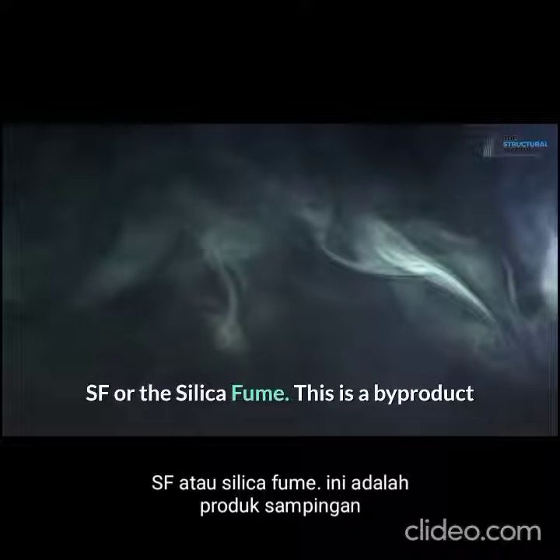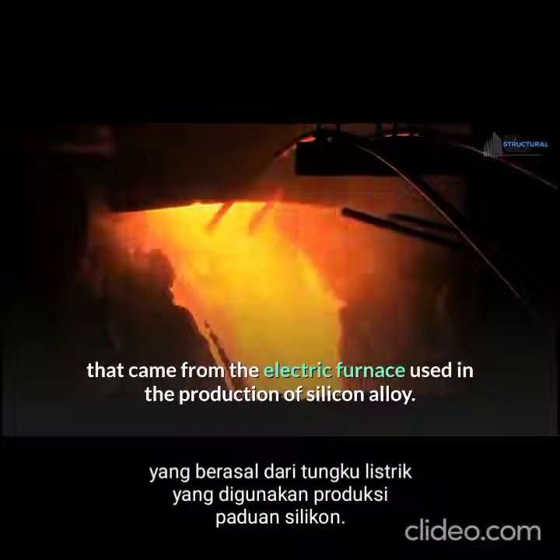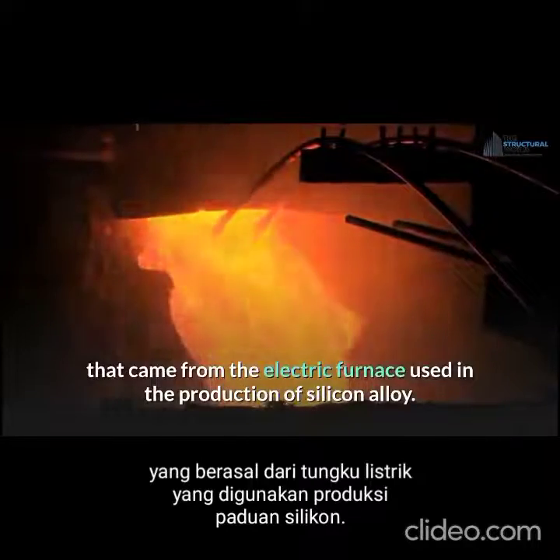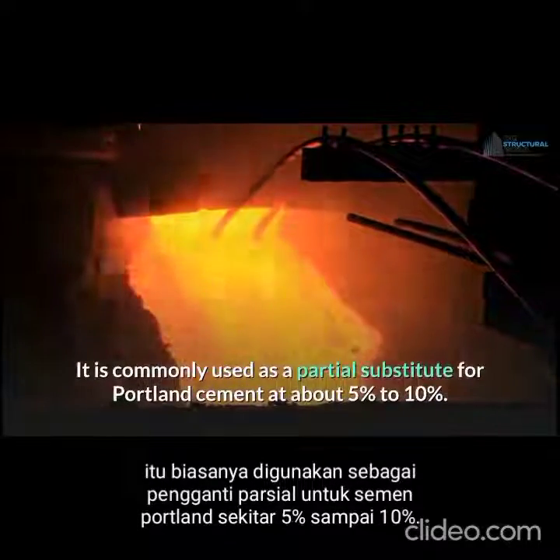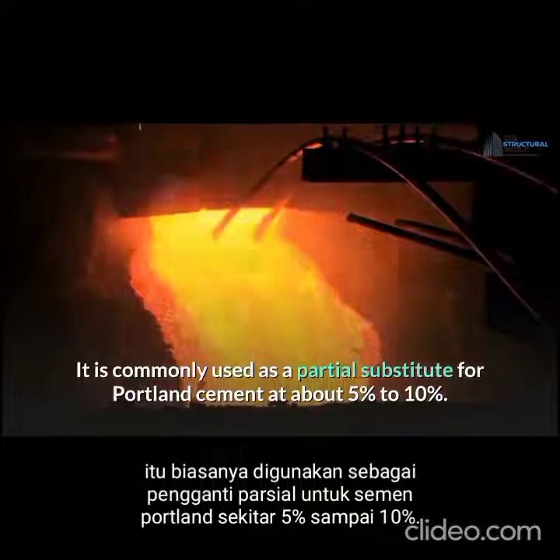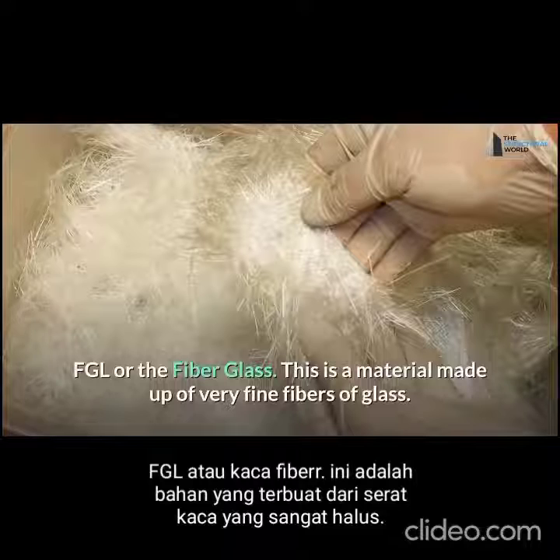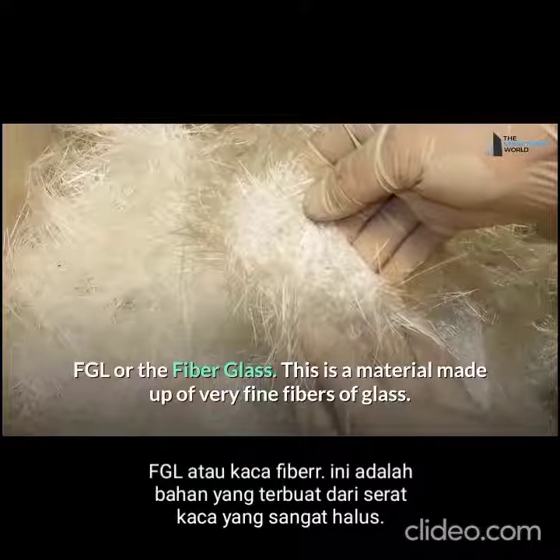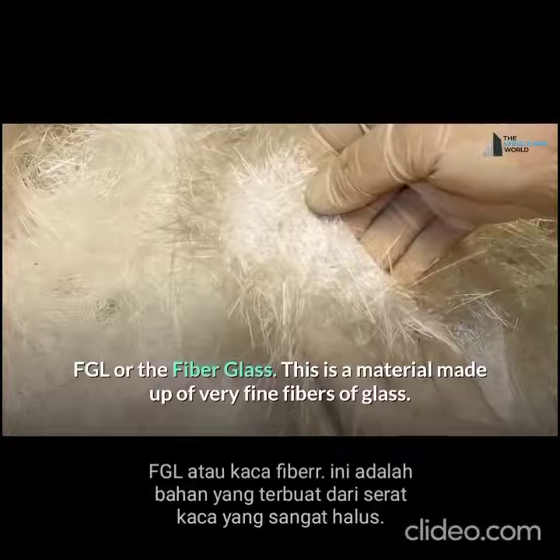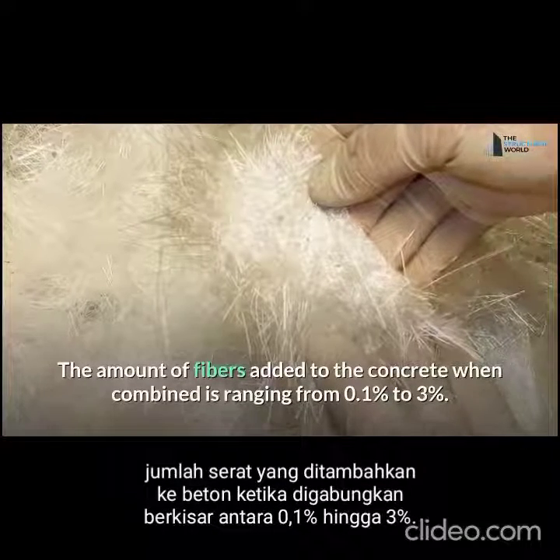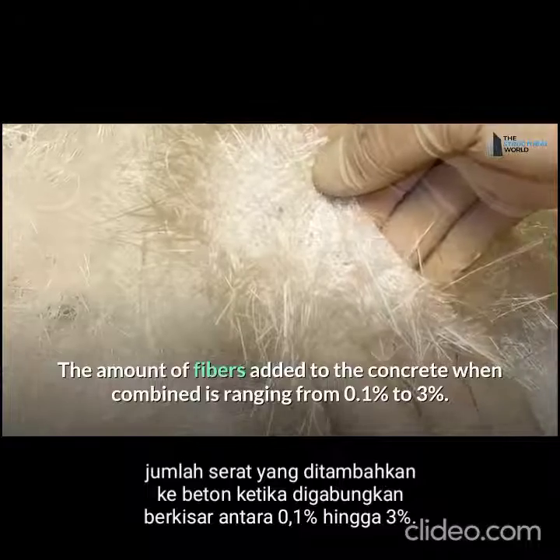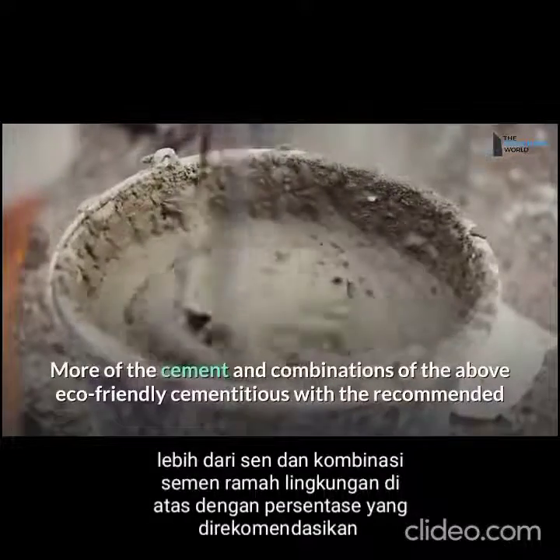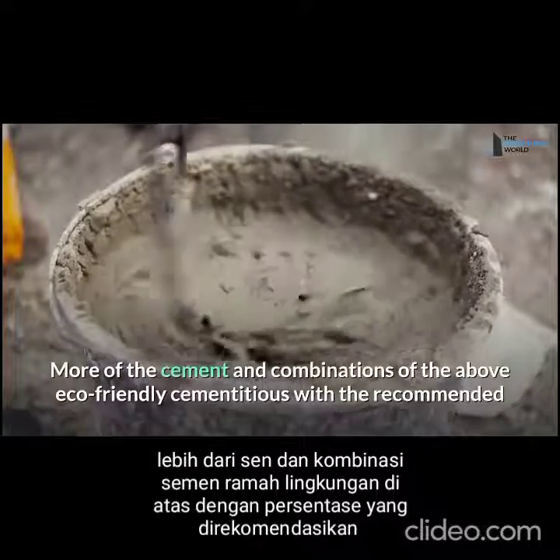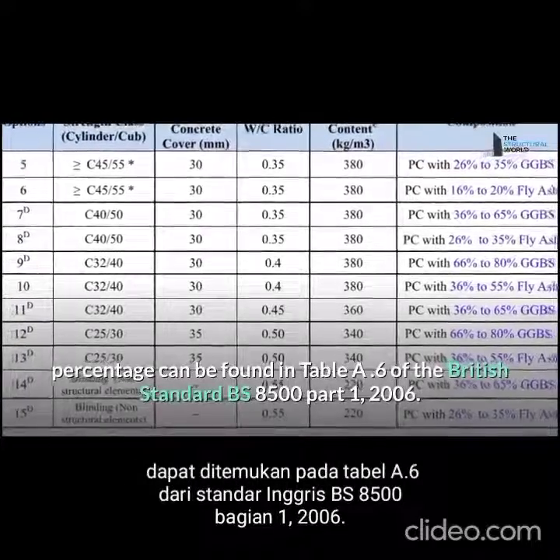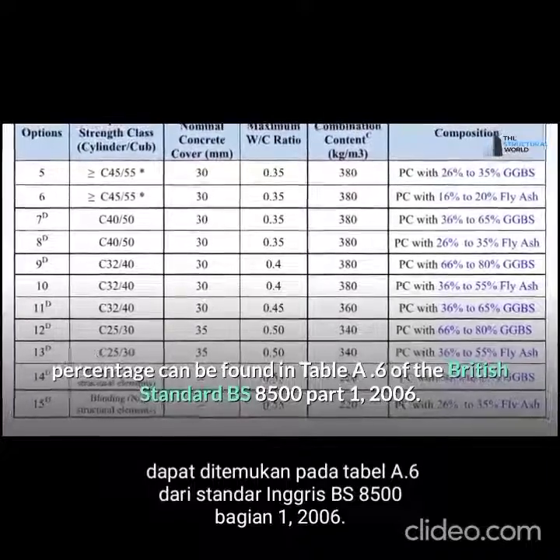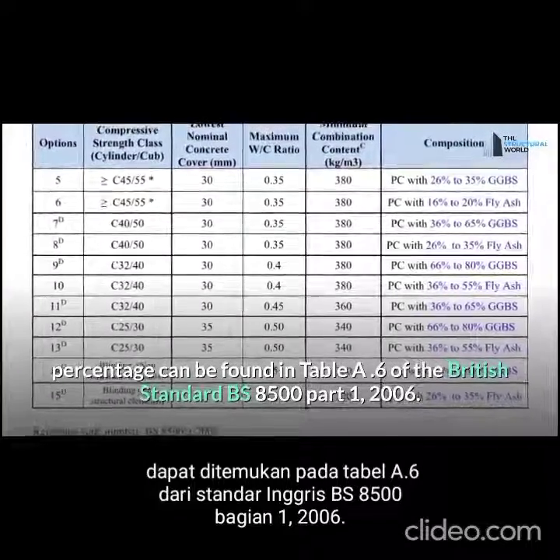SF, or silica fume. This is a byproduct that comes from the electric furnace used in the production of silicon alloy. It is commonly used as a partial substitute for Portland cement at about 5% to 10%. FGL, or fiberglass. This is a material made up of very fine fibers of glass. The amount of fibers added to the concrete ranges from 0.1% to 3%. More of the cement and combinations of the above eco-friendly cementitious materials with the recommended percentages can be found in Table A.6 of the British Standard BS 8500 Part 1, 2006.